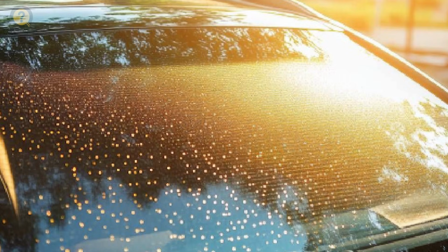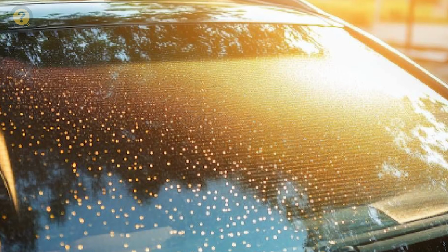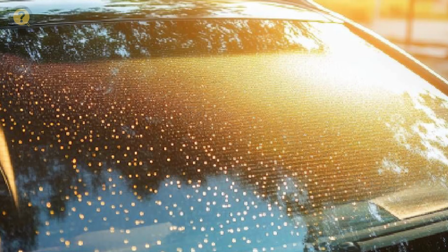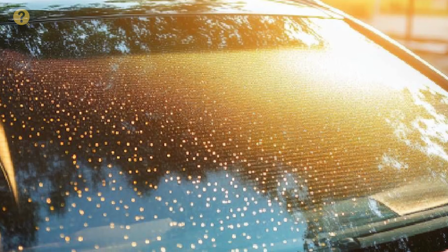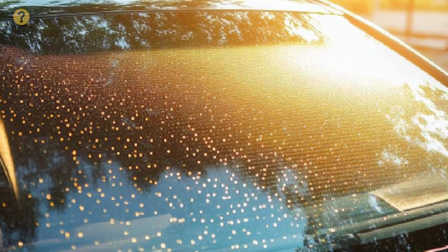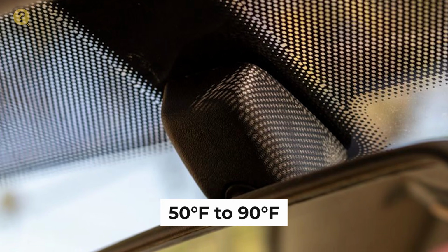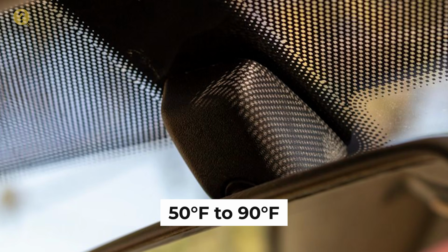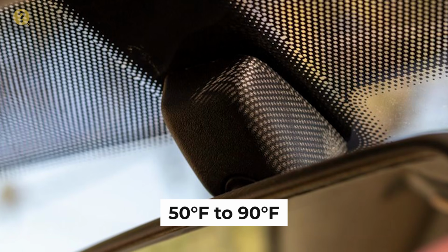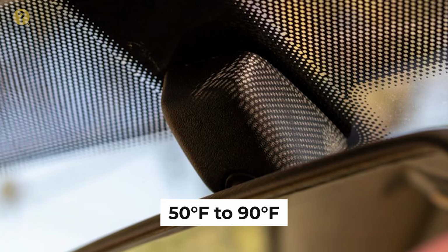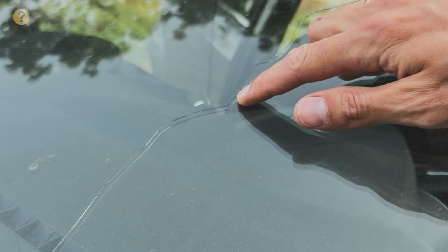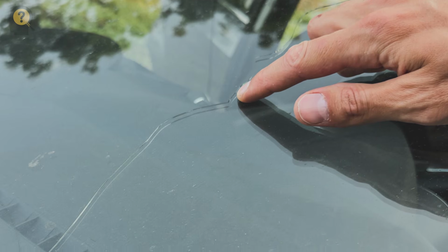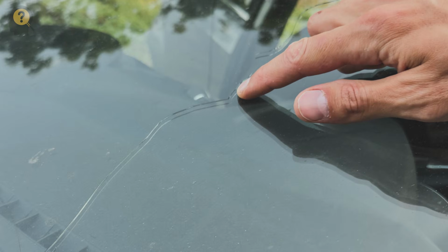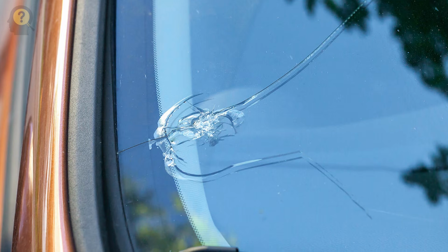When sunlight hits that solid black ceramic border, it absorbs heat much faster than the clear glass next to it. On a hot summer day, the temperature difference between the black ceramic border and the middle section of the glass can reach 50 degrees Fahrenheit to 90 degrees Fahrenheit, 28 degrees Celsius to 50 degrees Celsius in just a few minutes. If one section of the windshield expands rapidly and the adjacent section hasn't had time to expand, it will cause stress and eventually lead to cracking.